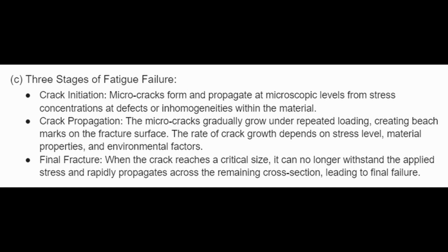2. Crack propagation. The micro cracks gradually grow under repeated loading, creating beach marks on the fracture surface. The rate of crack growth depends on stress level, material properties, and environmental factors. 3. Final fracture. When the crack reaches a critical size, it can no longer withstand the applied stress and rapidly propagates across the remaining cross-section, leading to final failure.